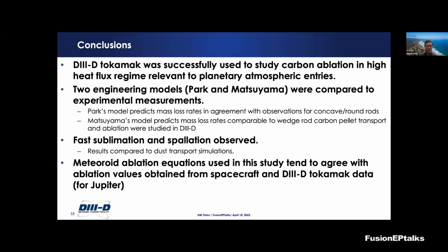We've noticed that Matsuyama's model over-predicts the loss rates, but is more close to the wedge-shaped rods in our experiments. We also observed both fast sublimation and spallation in those experiments, and we compared the results to our dust transport simulations.